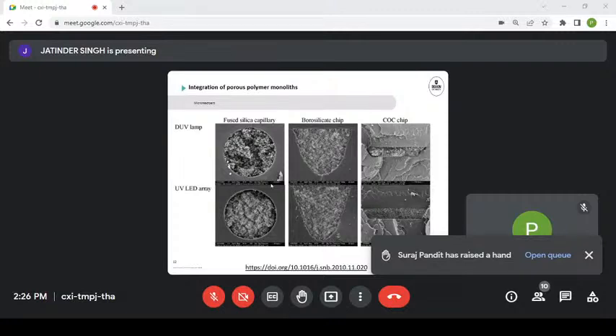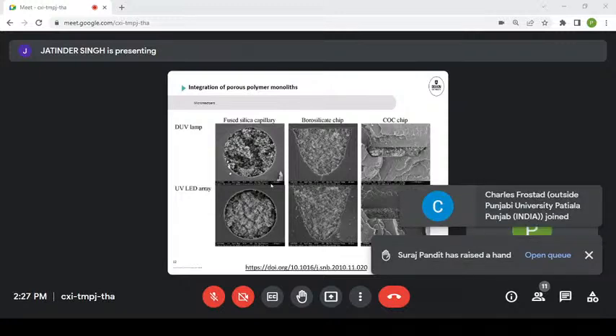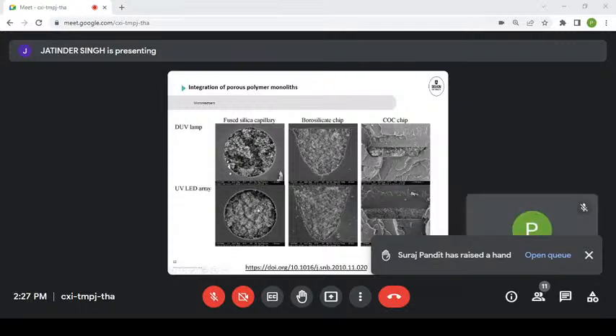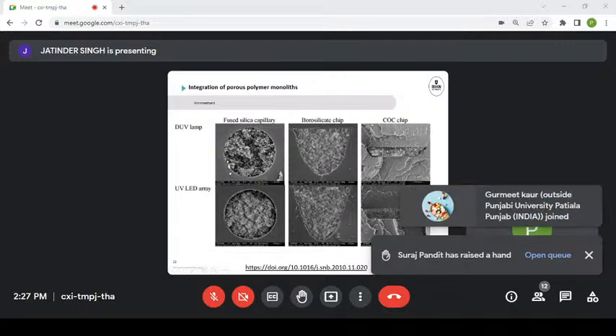The UV LED array was $300, so we have a significantly lower cost in our lamp. The price for us to pay is that it's a little bit lower intensity UV light, so we had to wait a little bit longer. But as you can see, with the UV LED array, we could also make our polymer monoliths in fused silica capillary, in glass microchannels, and in polymer microchannels.